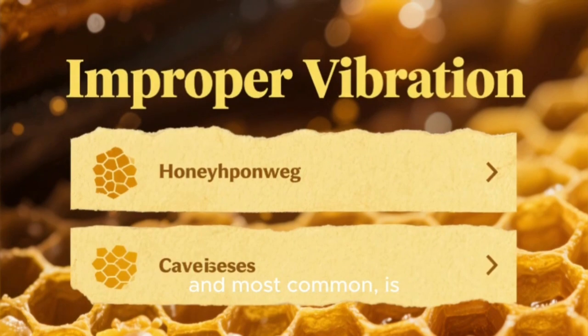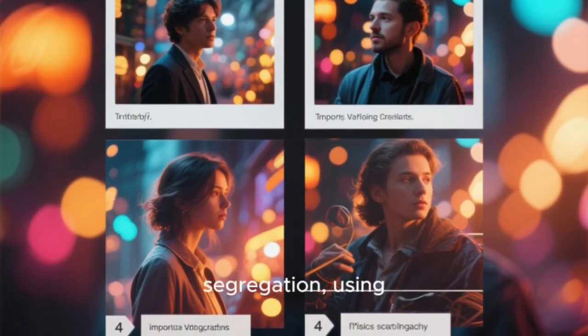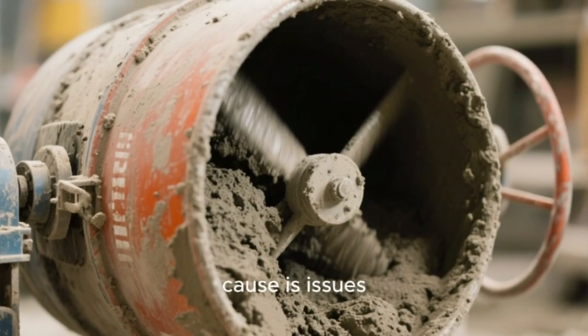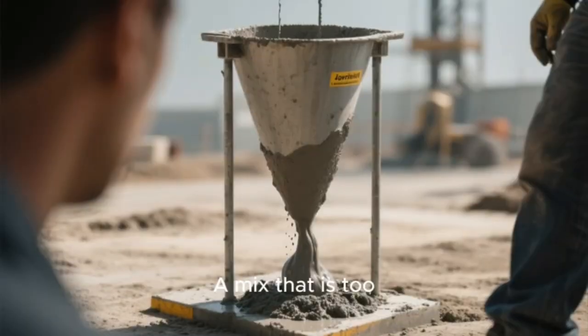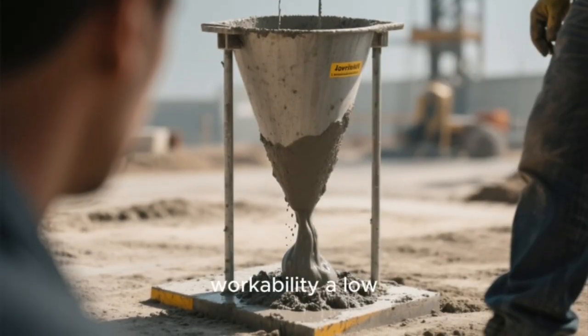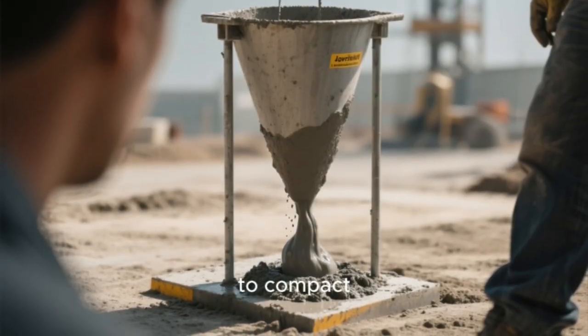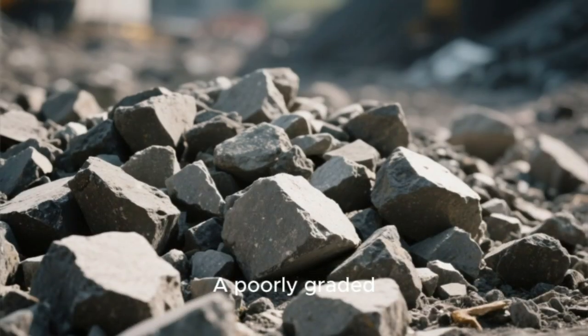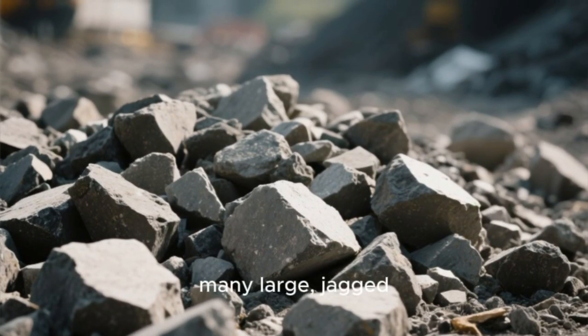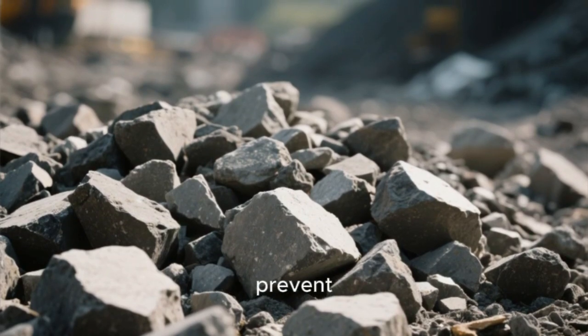So, what are the specific causes? We can break them down into three main categories. First, and most common, is improper vibration. This includes not vibrating enough, vibrating too much, which causes segregation, using a vibrator with the wrong frequency or diameter for the formwork, or simply missing sections altogether. The second major cause is issues with the concrete mix design. A mix that is too stiff or has poor workability, a low slump, is difficult to compact, especially around tight reinforcement. A poorly graded aggregate with too many large, jagged pieces can also lock together and prevent consolidation.